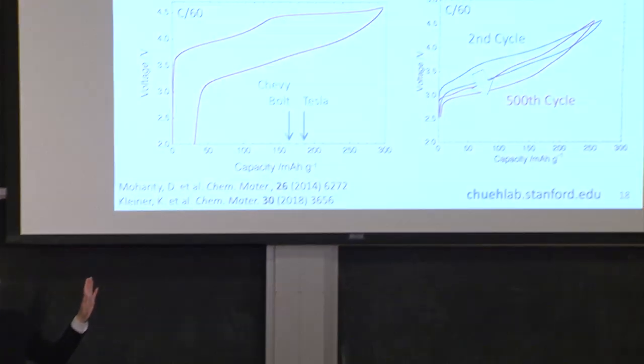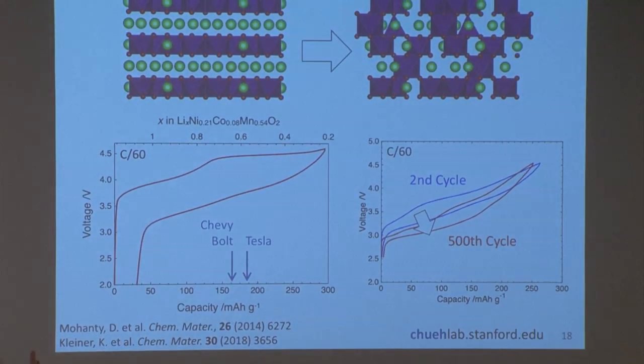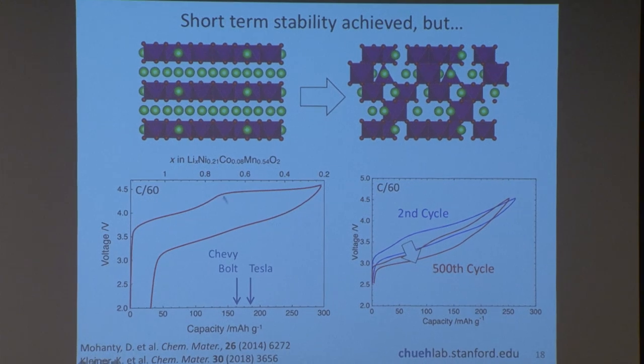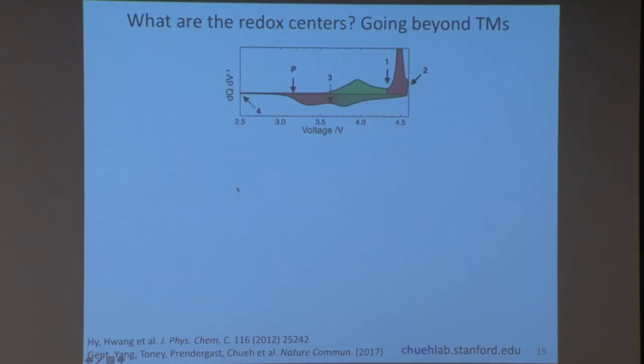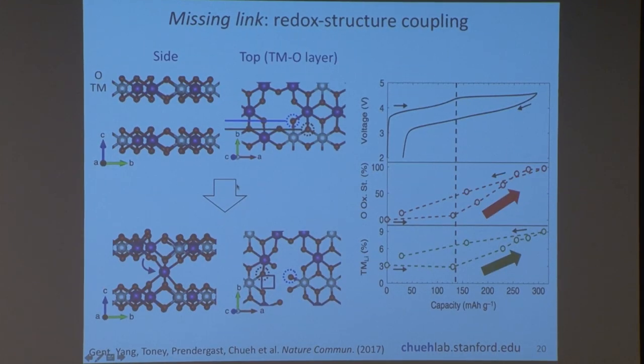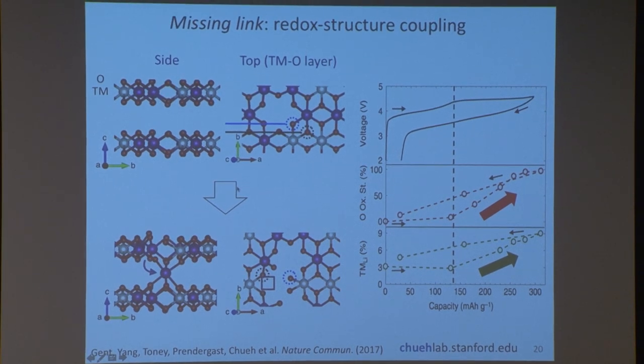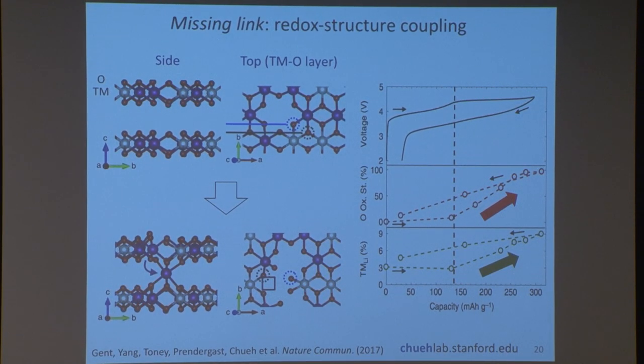This is an excellent question. So I'll direct you to this plot here. The ejection of these, the transition metal migration, happens right around here. Okay, so maybe I can show this one here. So when you remove about 0.5 formula units of lithium from this material, the transition metal begins to move and the oxygen is oxidized. So it's this second half here on the right that's coming from the oxidation of oxygen.